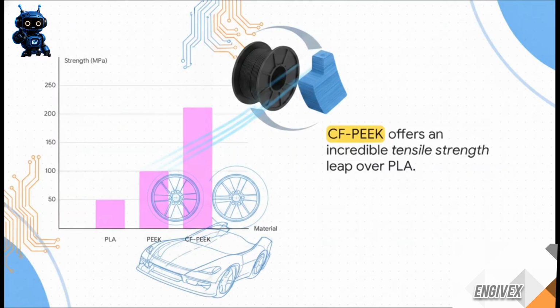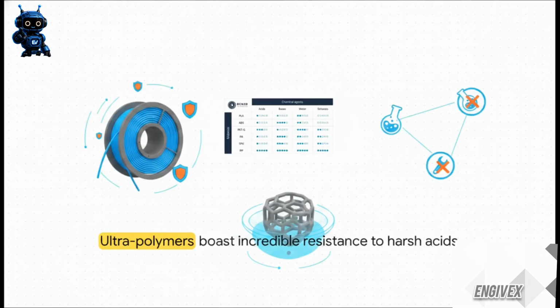If you really want to see how far the technology has come, just look at this jump in raw strength. Standard PLA has a tensile strength of around 50 megapascals. Standard PEEK doubles that, to about 100 megapascals. But when you reinforce PEEK with continuous carbon fiber, the tensile strength jumps to a jaw-dropping 212 megapascals. At this point, we are completely blurring the line between plastic and metal, which allows for extreme lightweighting in automotive and aerospace applications.